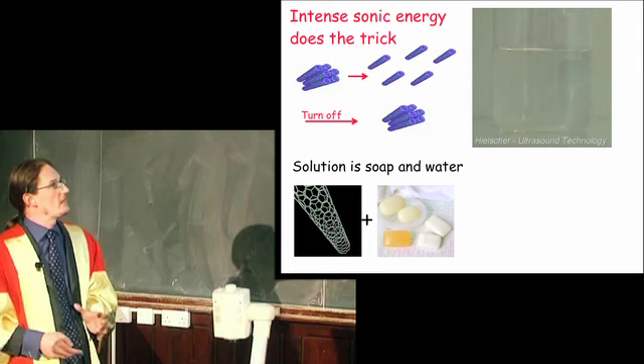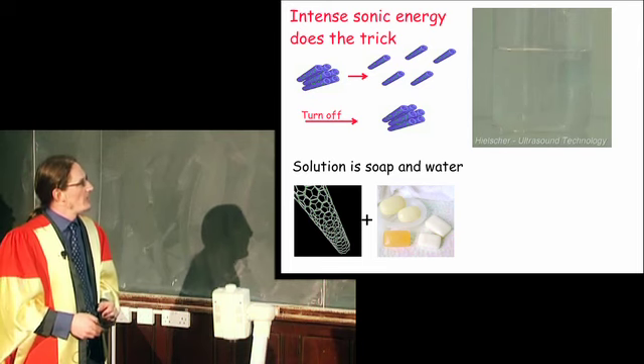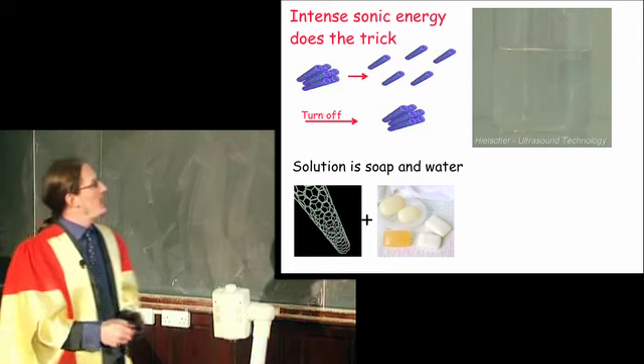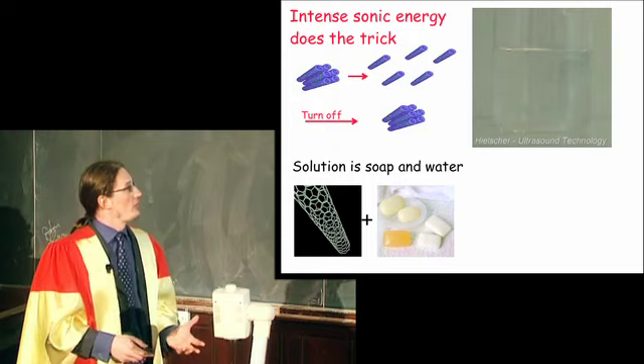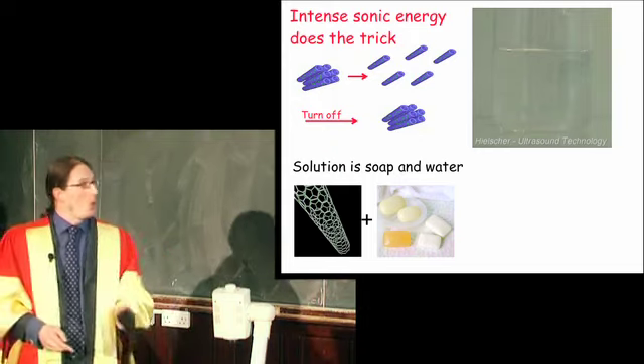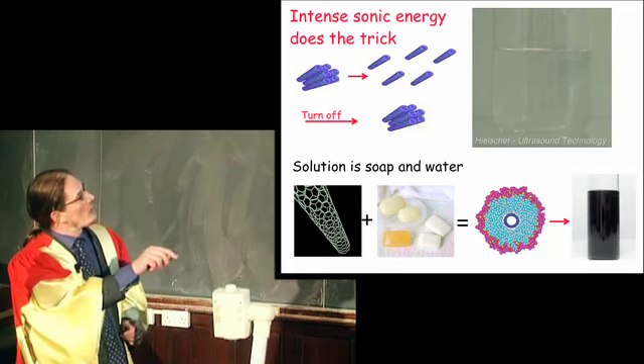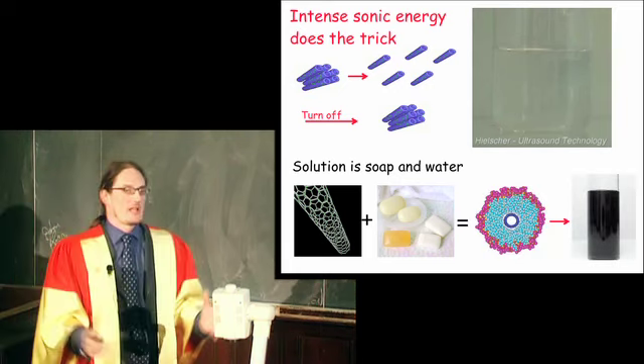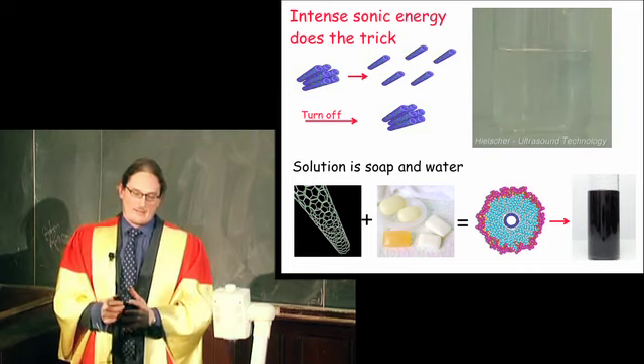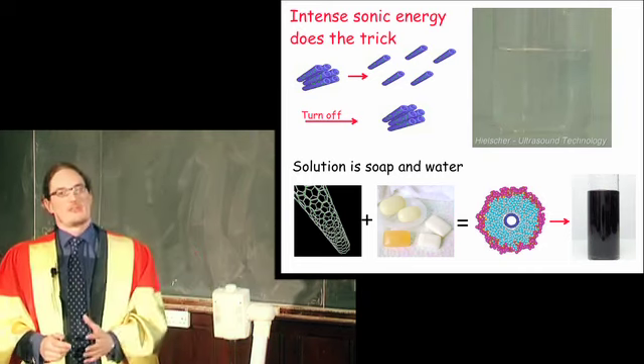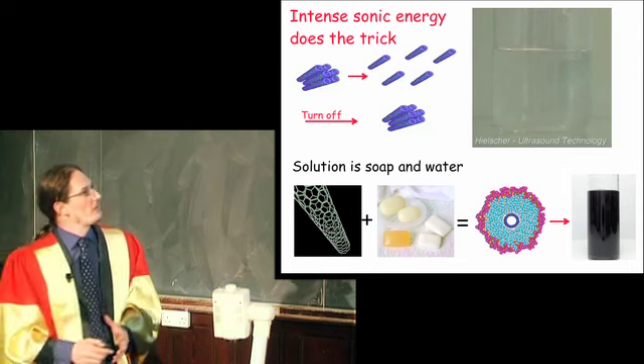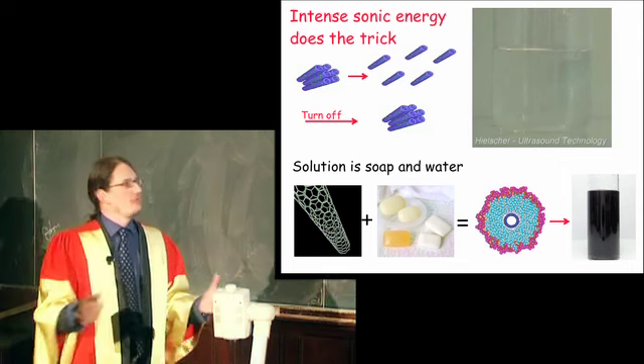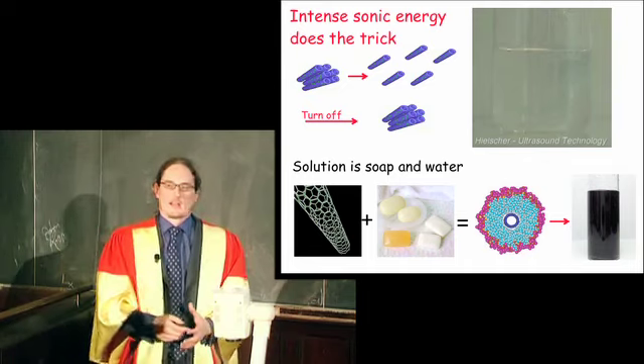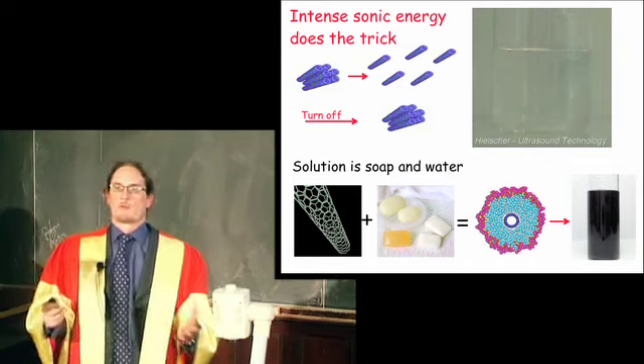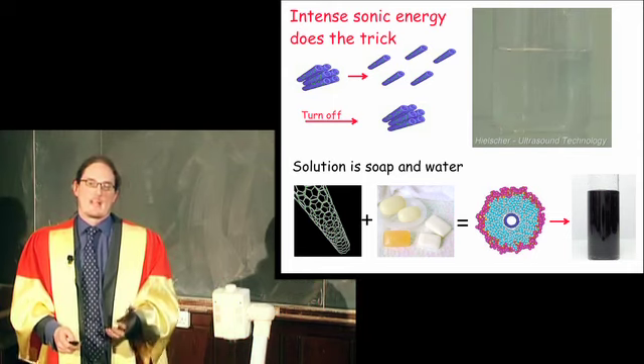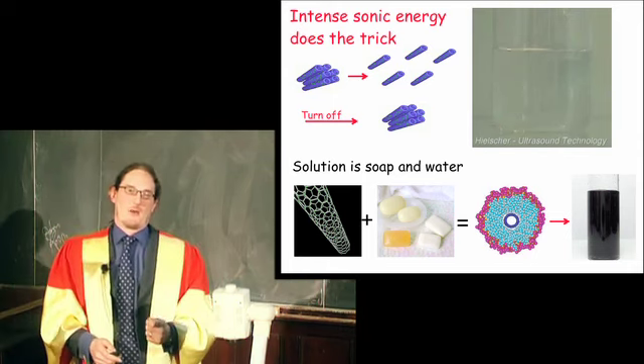This isn't something that we discovered, but we did a lot of work to characterize it. It was found that if you just take your nanotubes, put them in water, and add a small amount of soap, the soap coats the nanotubes, and this stops the nanotubes from reaggregating. One of our small contributions to this area of research was, while everyone else was using soaps, surfactants in the parlance, that cost 300 euros per gram, we showed that Fairy Liquid does just as good a job.